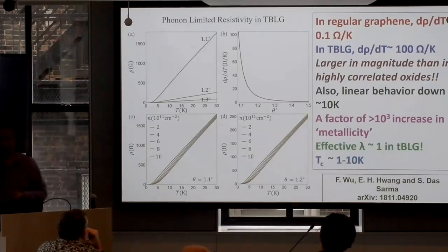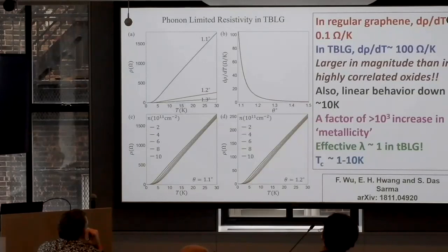Can you just comment or clarify why optical phonons are not important at all? You said high energy optical phonon. But there are many situations when the optical phonon matters, not in BCS or Migdal if the phonon energy is larger than the Fermi energy, but if it's lower, it doesn't have to be acoustic. No, here we looked into it carefully, it just doesn't contribute. It's not like I discarded them without considering them. They come into play when I talk about untwisted structures. We include that, and sometimes that enhances Tc slightly. So we have included them in some of the situations.